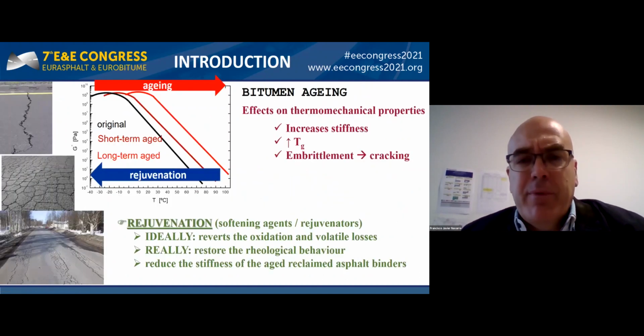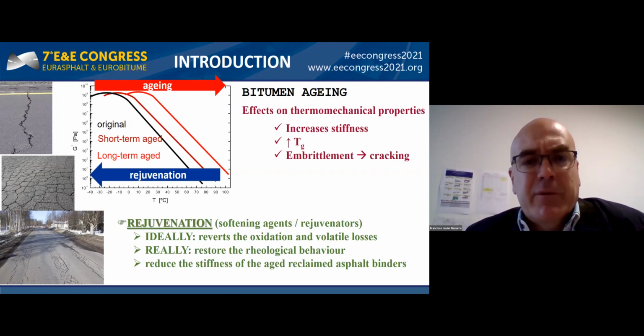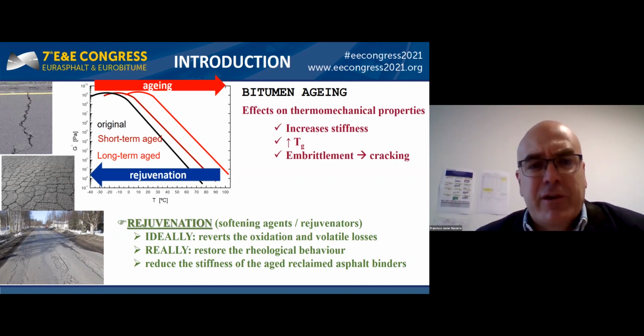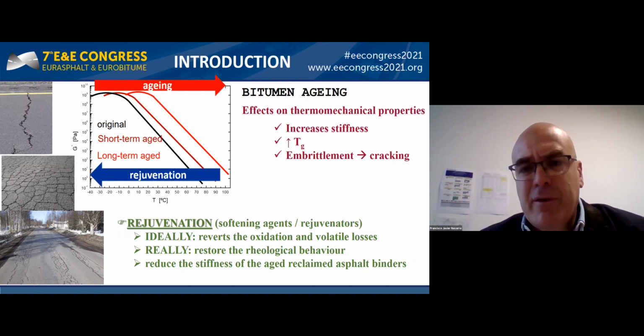From a rheological point of view, for example, if we focus on the loss modulus curve versus temperature, aging causes a shifting of the curve to the right, leading to larger values at every temperature and a clear increase in the mechanical glass transition temperature. The modification of this thermomechanical response causes the hardening that leads to cracking problems in the resulting pavement. In order to alleviate this problem, rejuvenators are usually employed.